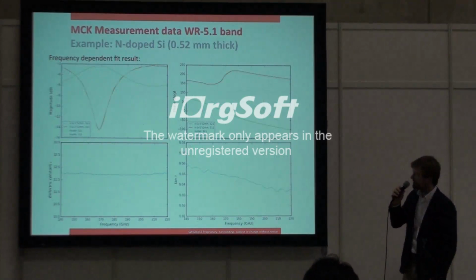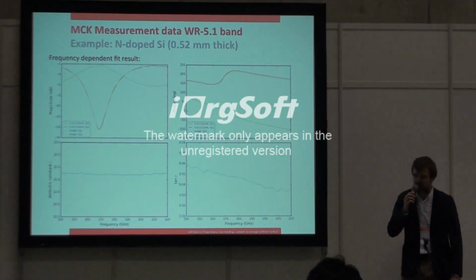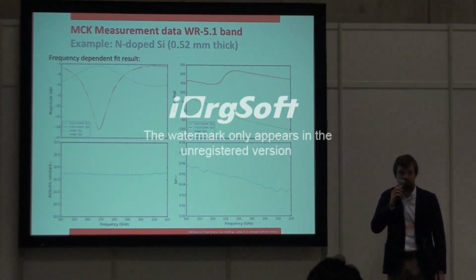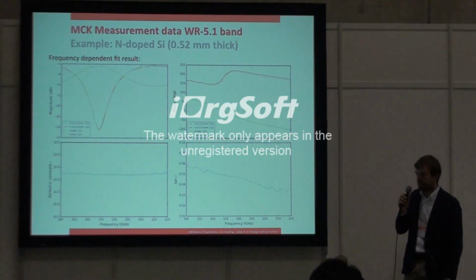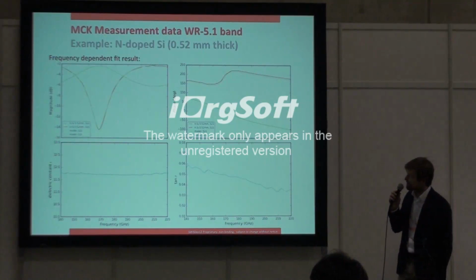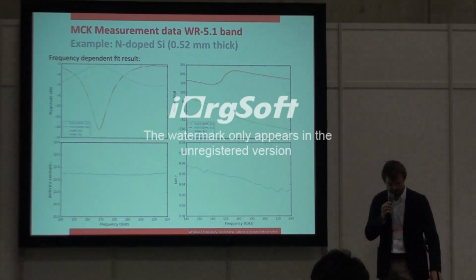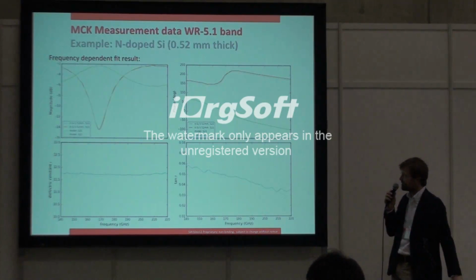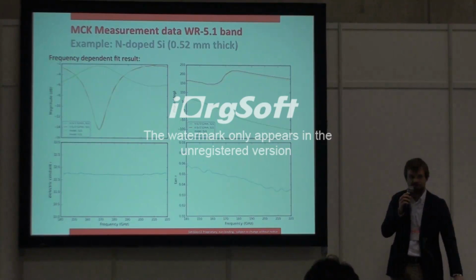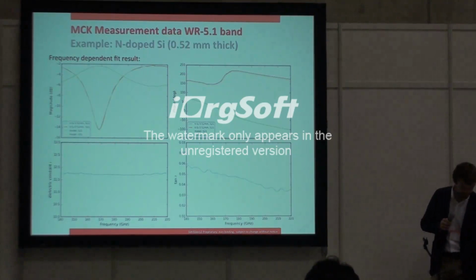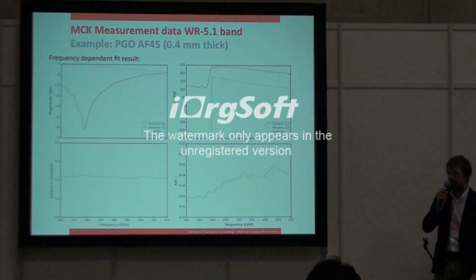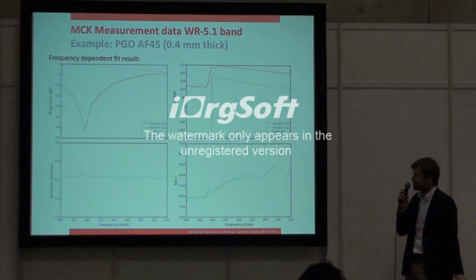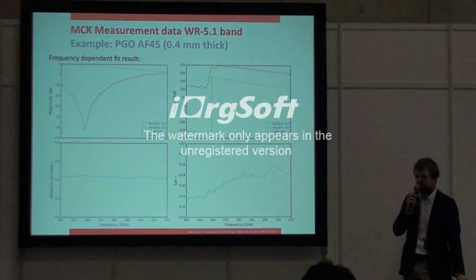For some materials, though, it is not entirely constant. In this example, we show a piece of n-doped silicon, so a piece of wafer, essentially, cut off 0.5 millimeter thick, for which we measure the S parameters. And we see that for this material, the constant permittivity model, again, shows some problems, so we have to move to the frequency-dependent permittivity model. And we see that actually, surprisingly, for this material, there is a slight decrease of the loss tangent as a function of frequency. Another ceramic material of another manufacturer, where again we see a frequency dependence of the permittivity. So in this case, an increasing loss tangent as a function of frequency.